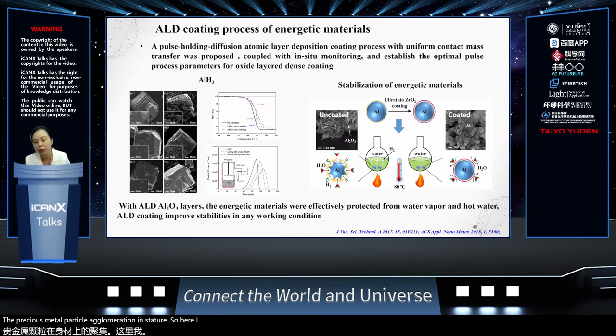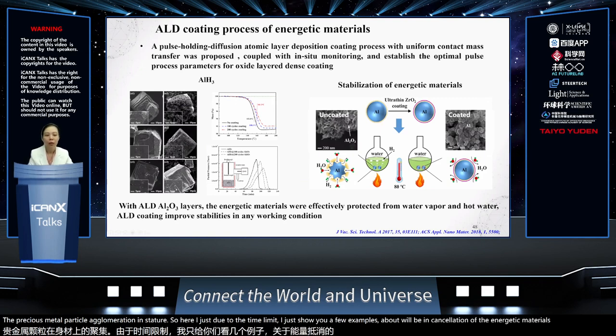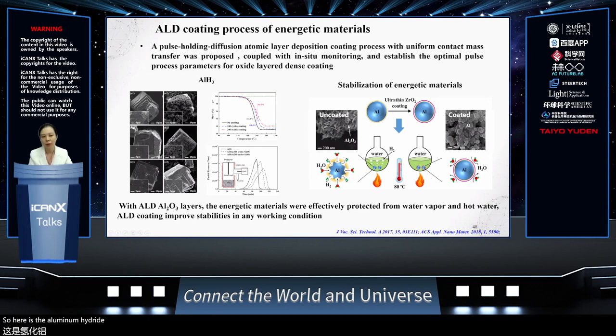Here, due to the time limit, I'll just show you a few examples about the encapsulation of energetic materials. So here is the aluminum hydride material. It's actually a good hydrogen storage material. It can be used for a lot of good applications. But as you know, the hydrogen will probably easily escape, especially if you store it for a while. To help with that, a thin layer of passivation becomes very important. You don't want to lose the volume energetic part of the hydrogen. At the same time, you want to keep it sealed very well.